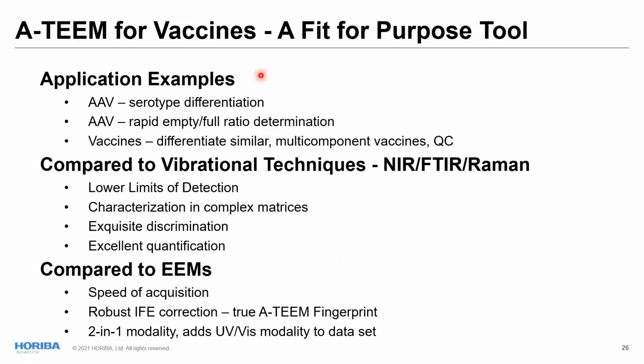So really, and I have personal experience trying to characterize vaccines with Raman and FTIR, and the ease with which A-TEEM can tackle this problem is really exciting to me. We were able to differentiate between AAV2 and 9 serotypes, also able to do a rapid empty-full ratio determination of the AAV9, looking at very similar multi-component vaccines, able to do robust differentiation and classification of the different vaccine types. A-TEEM has much lower limits of detection, which is extremely helpful specifically for the vaccine samples.